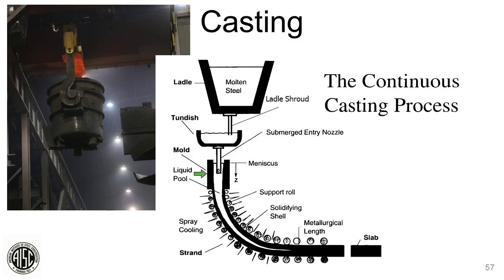What's interesting about a continuous caster, it's not solid when it comes out the bottom. You basically have an outer shell that is solid, an inner core that is still liquid, that proceeds all the way down to the end of the machine, and we call the end of it the metallurgical length. And the metallurgical length better end before you get to the torch, because you can imagine what happens if you cut the core, it's still liquid, shoots out the end. So we don't want that to happen. That's a bad day. So next slide, please.